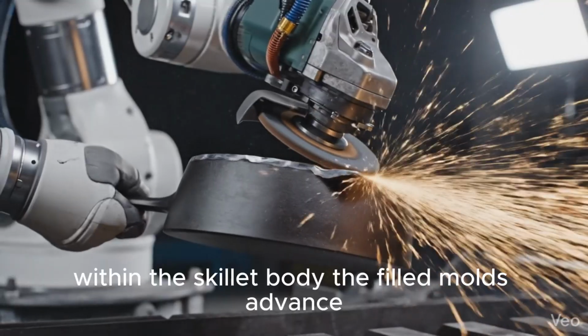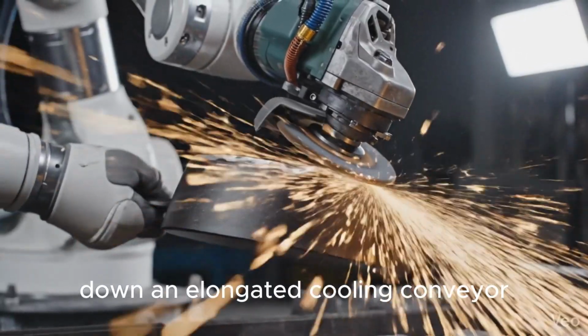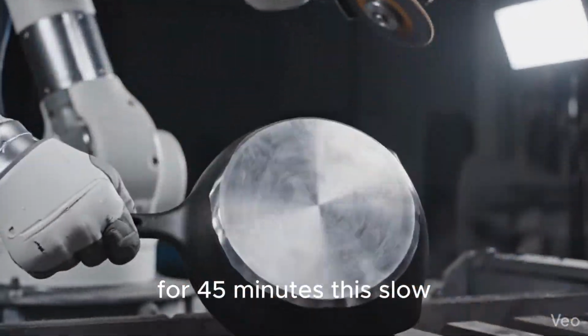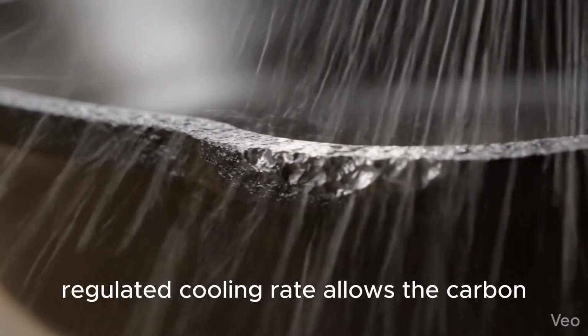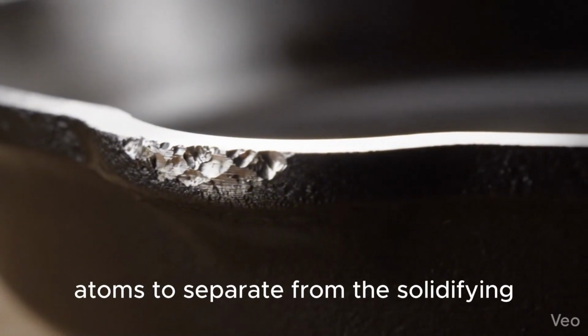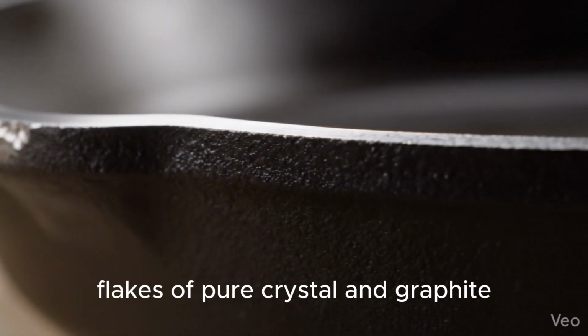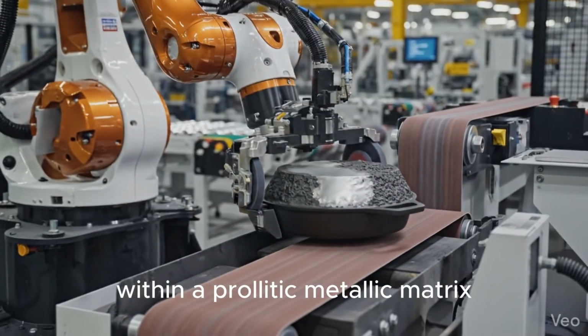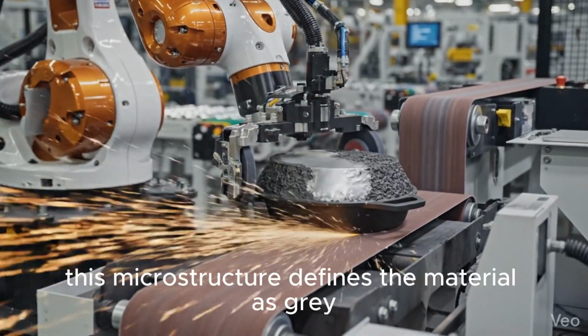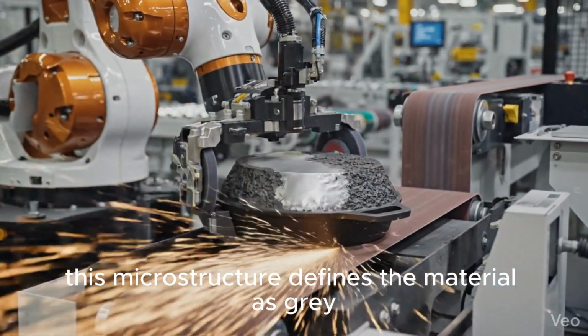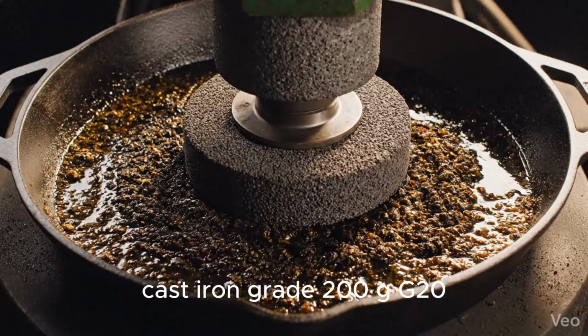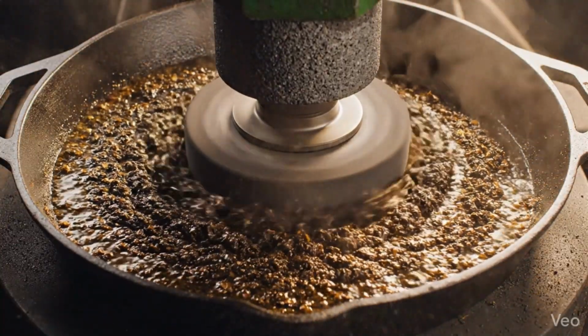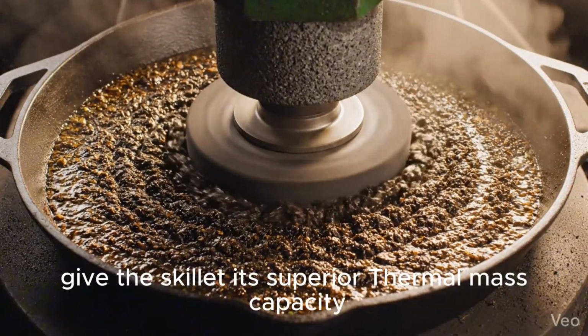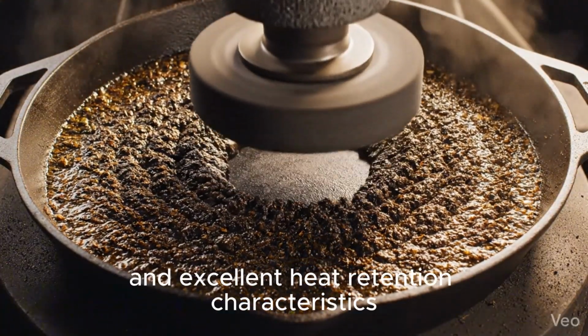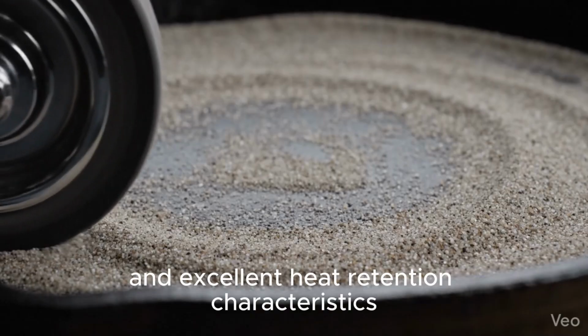The filled molds advance down an elongated cooling conveyor for 45 minutes. This slow, regulated cooling rate allows the carbon atoms to separate from the solidifying iron solution, forming interconnected flakes of pure crystalline graphite within a pearlitic metallic matrix. This microstructure defines the material as gray cast iron, grade 200, Gg20. The graphite flakes give the skillet its superior thermal mass capacity and excellent heat retention characteristics.